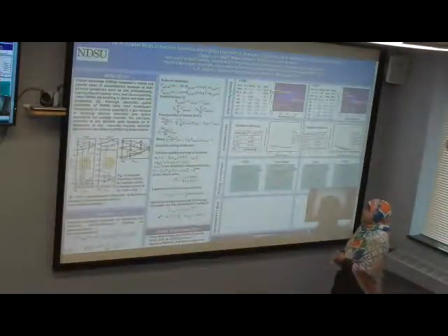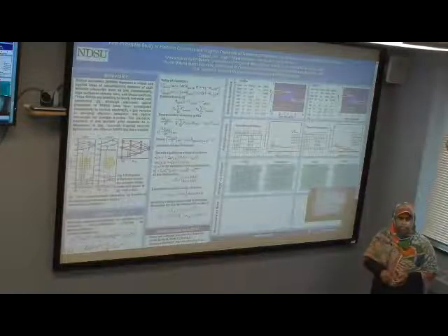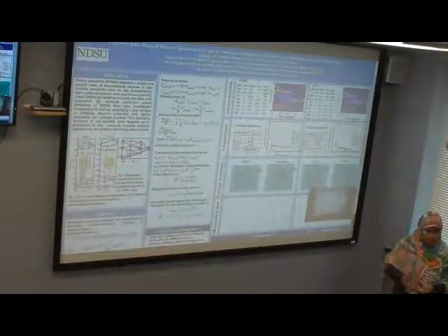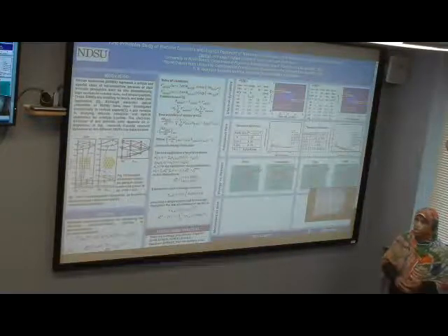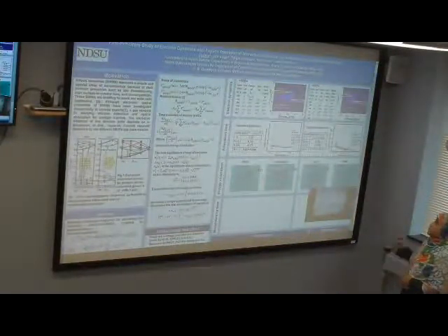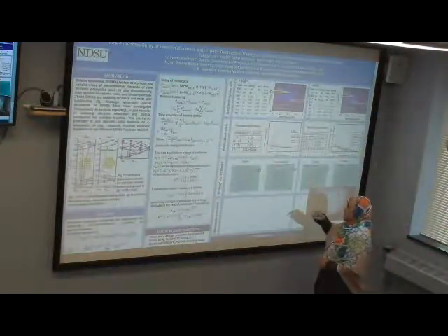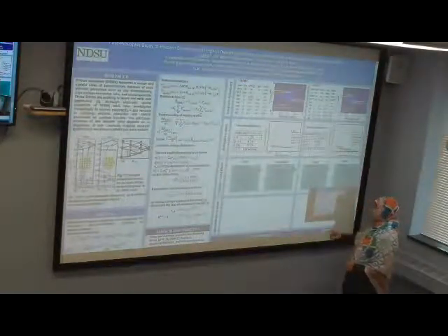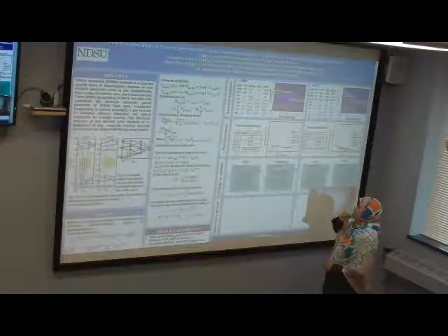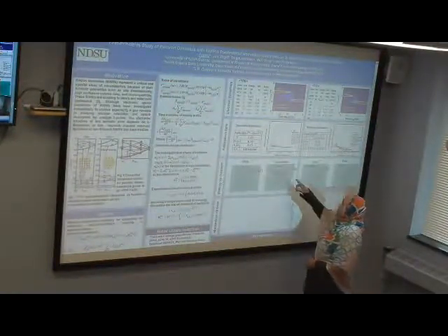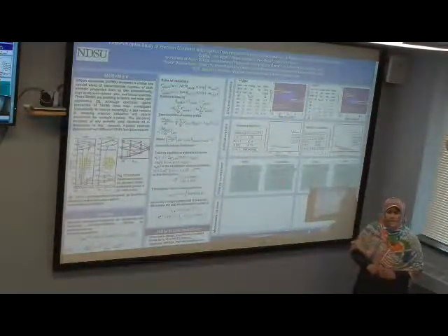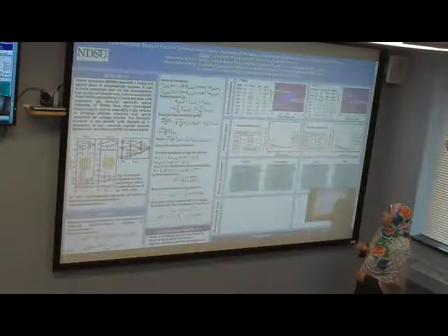Then I calculated, for each nanowire and each k point, the relaxation rate for 10 different states. And then I calculated the relaxation time from the relaxation rate. Then I took the natural logarithm of that relaxation time and made graphs. The x-axis represents the dissipated energy, the energy difference between the band state and that corresponding excited state.